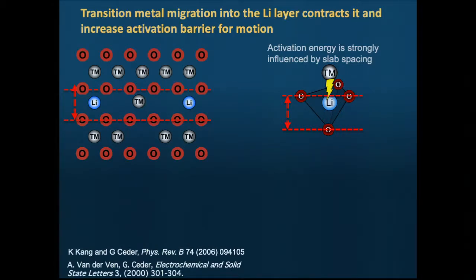And the reason is quite simple. This is essentially an ordered rock salt. So it's an FCC packing of oxygen. The cations sit in octahedral sites. And to migrate from one octahedral site to another octahedral site, they have to go through a tetrahedral site. That's just the crystallography of the FCC. If you ever stare at it carefully, on every face of an octahedron is a tetrahedron. And this is the activated state. When lithium is in the activated state, it's very close to the transition metal. So this electrostatic repulsion controls the activation energy for lithium diffusion.